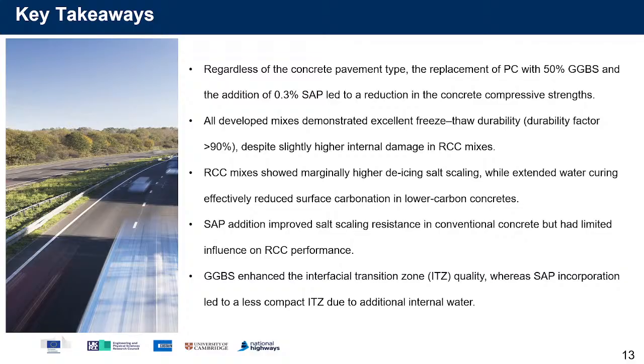Here are some key takeaways from this presentation. Regardless of the concrete pavement, the replacement of Portland cement with 50% GGBS and the addition of 0.3% SAP resulted in a reduction in the concrete compressive strength. All developed concrete mixes demonstrated excellent freeze-thaw durability factors, more than 90%, despite slightly higher internal damage in RCC mixes. RCC mixes show marginally higher de-icing salt scaling, while extended water curing effectively reduced the surface carbonation